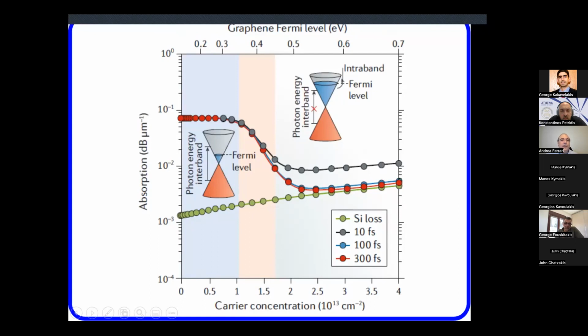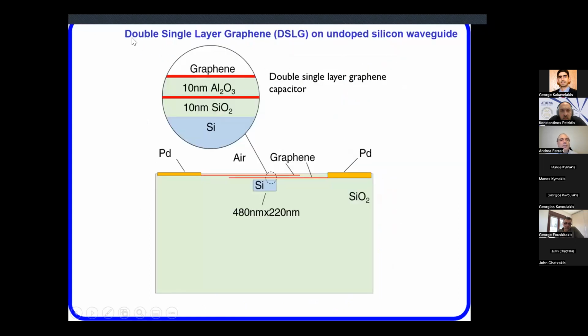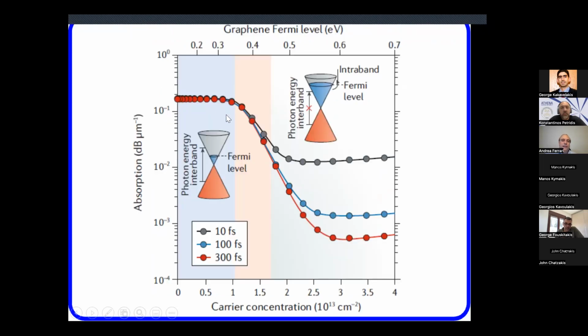So that's why we are using this term, double single layer graphene, which seems a weird term. Why don't we call it double layer graphene? It's not a double layer because there are 2 individual layers of graphene separated by a dielectric. And if you do that, you can get rid of the silicon influence and then really get a massive improvement in properties if you have a very high quality graphene.